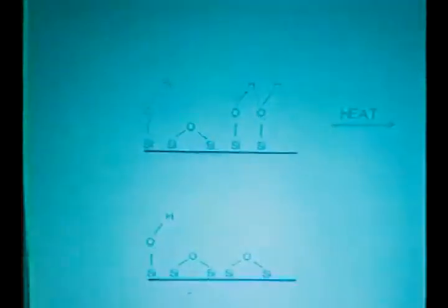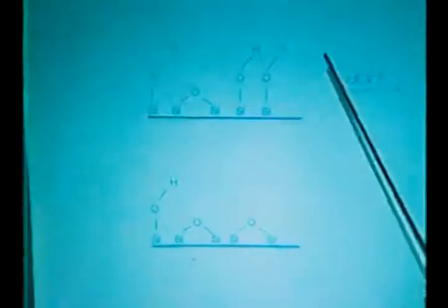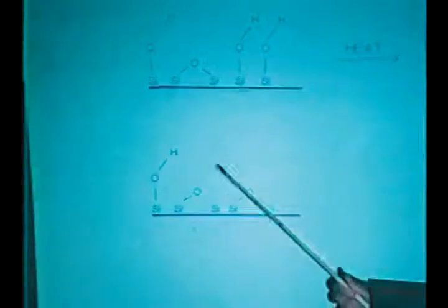So in terms of the model of the surface, if you take your silica gel with non-hydrogen bonded and hydrogen bonded silanols and heat it at 600 degrees C for a few hours, these condense to split out water. You get the new siloxane linkage, and then you have the non-hydrogen bonded silanols left to do chemistry on later.